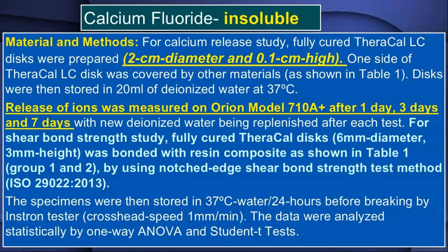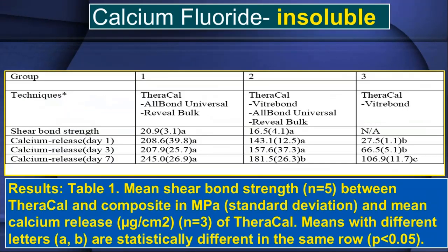I wanted to see what it did to the overall strength of the materials when you did this, because, you know, Vitrebond does not bond well to composite. It has to weaken it. And sure enough, of course, it does. It makes it weaker, without a doubt, right? The shear bond strength drops when you add Vitrebond to it. If you just do TheraCal, AllBond Universal, and Reveal bulk fill, you have a much stronger system. But also, look at the difference in the shear bond strength.